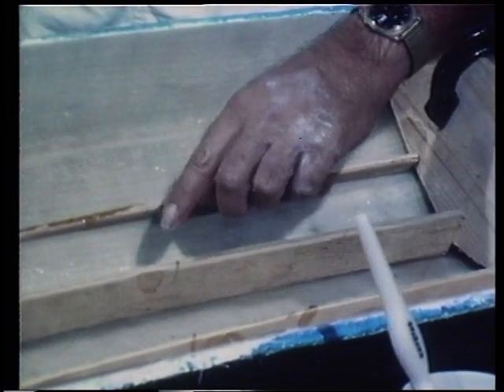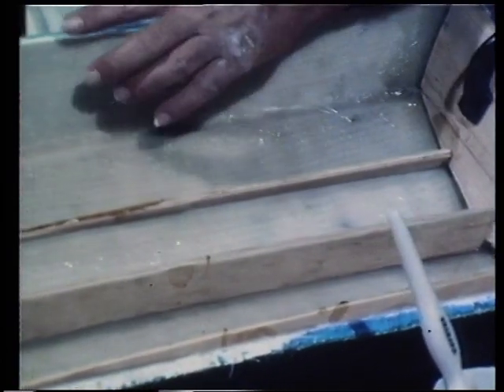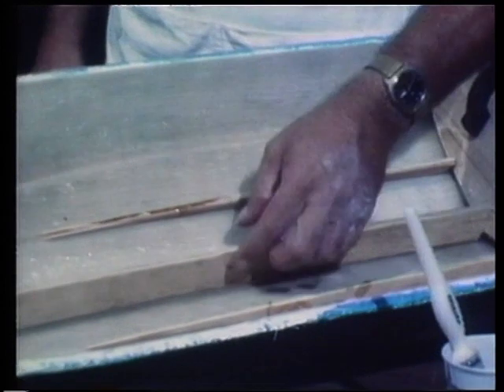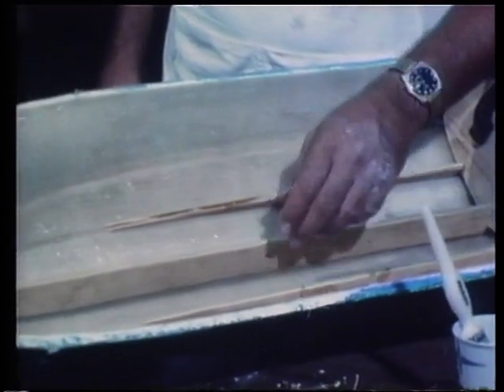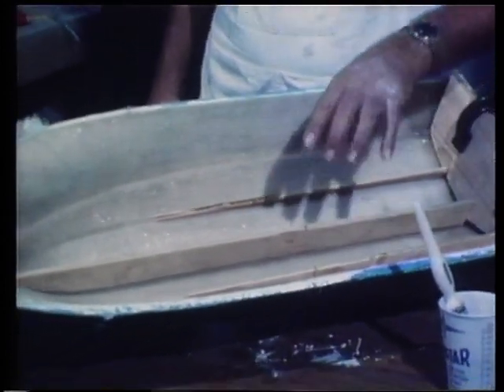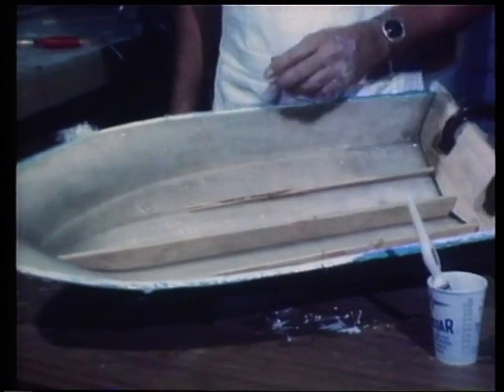Now, one thing about this, fiberglass will not go over a tight edge, so you must round the top corners of the stringers before you actually apply them in the boat. We'll come back when that's cured and put the rest of the laminate over.